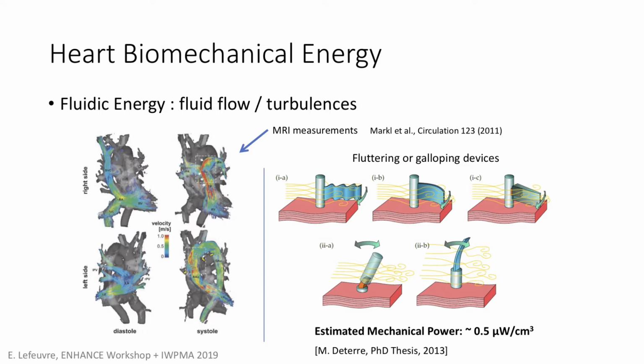So typically it was in the range of 0.5 microwatt per cubic centimeter. So it's not enough, because we need at least, let's say, between 1 and 5 microwatt to power this kind of device. And if you think about the loss in conversion, of course, we have almost nothing after conversion.